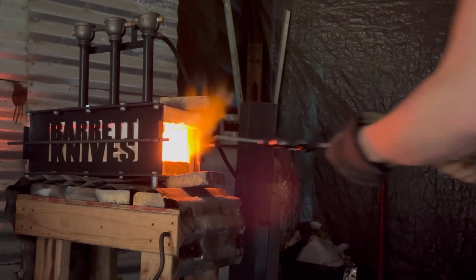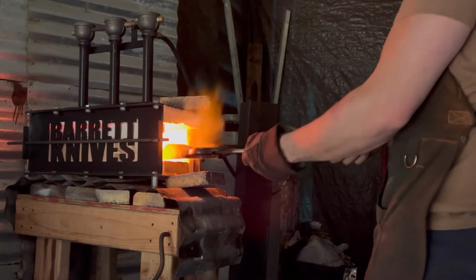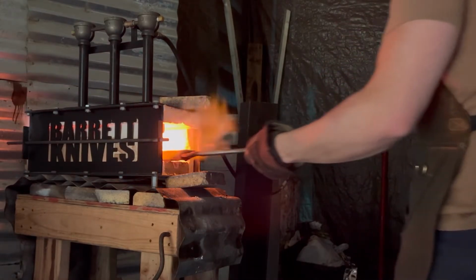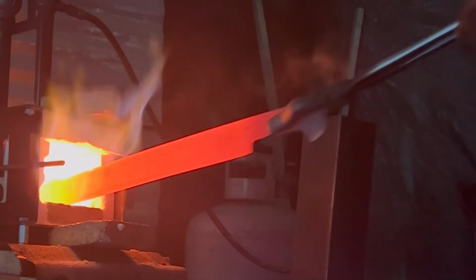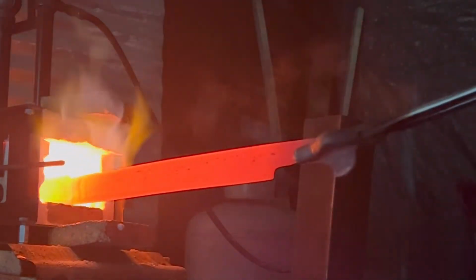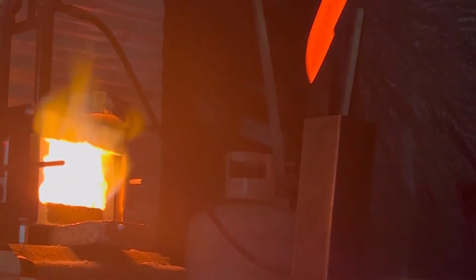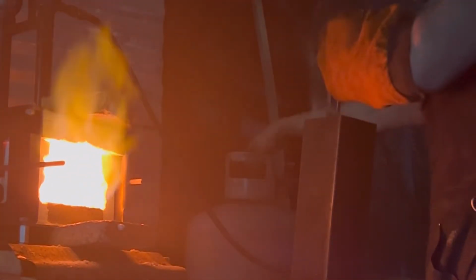Watch almost any episode of Forged in Fire and you'll see that a blade will break from use and you'll see a dark line. Usually that's because it was quenched too hot or it wasn't normalized properly, and then that grain structure was very, very coarse and open. So therefore it was very brittle and there was a stress fracture in there, possibly from working it too cold, whatever the case is. There are so many different things to watch out for.